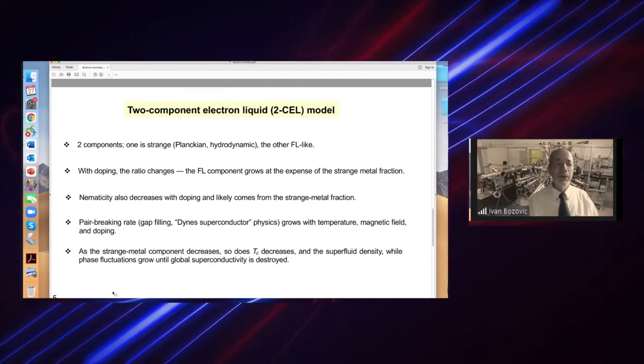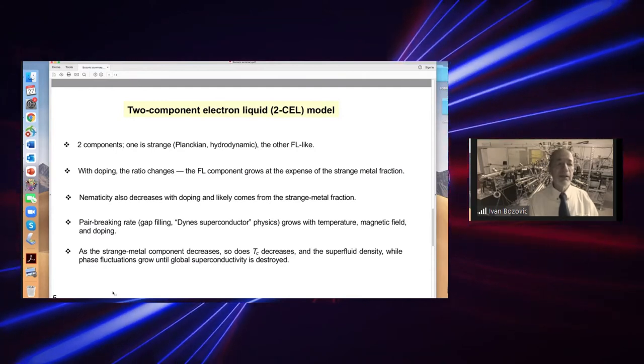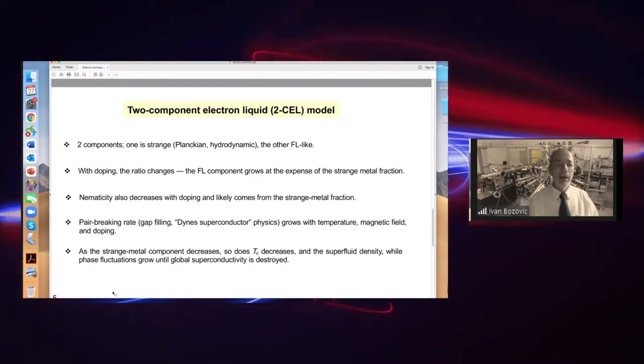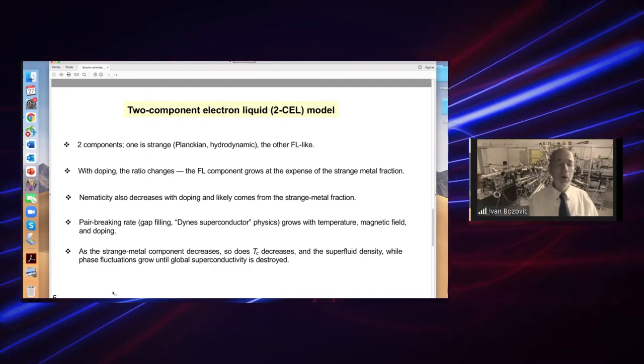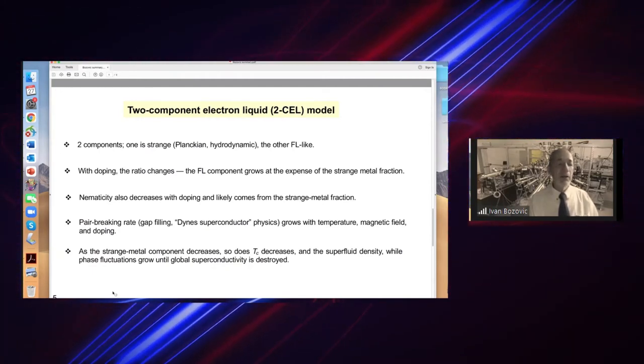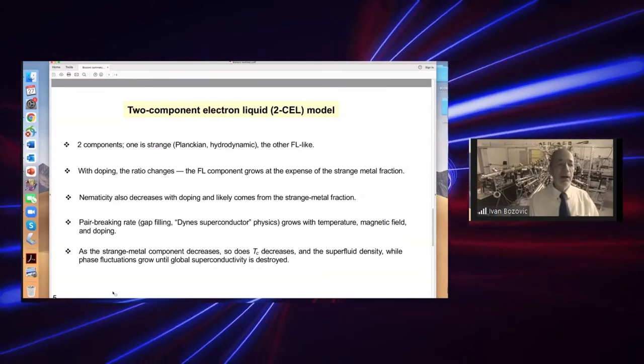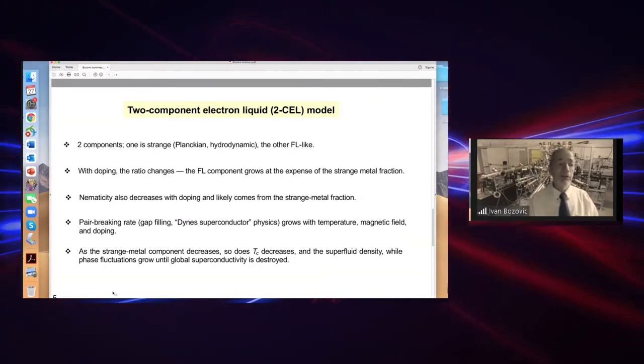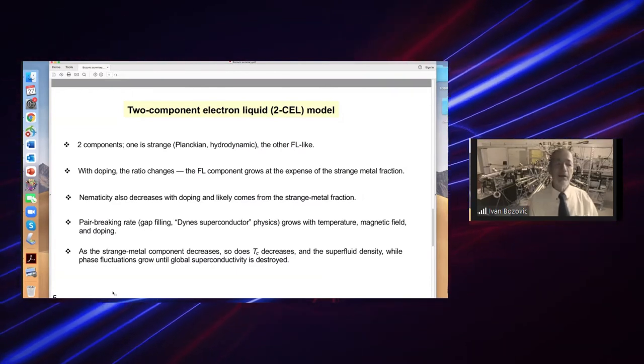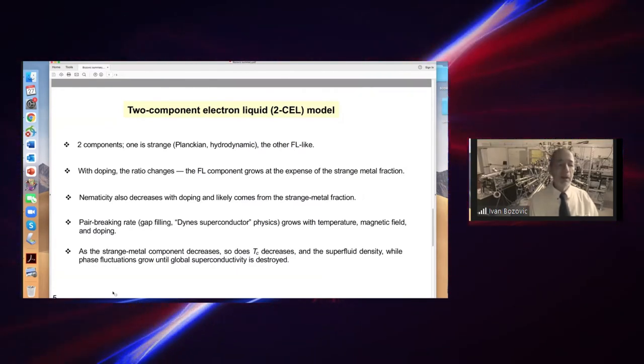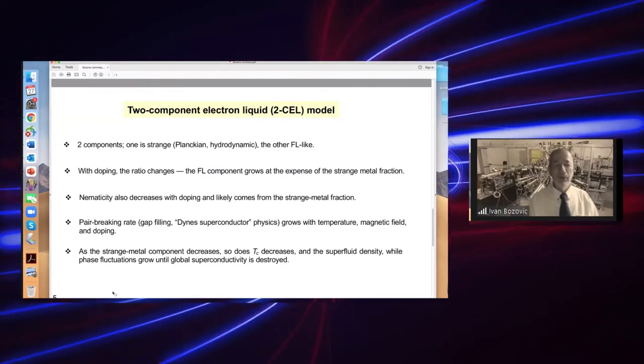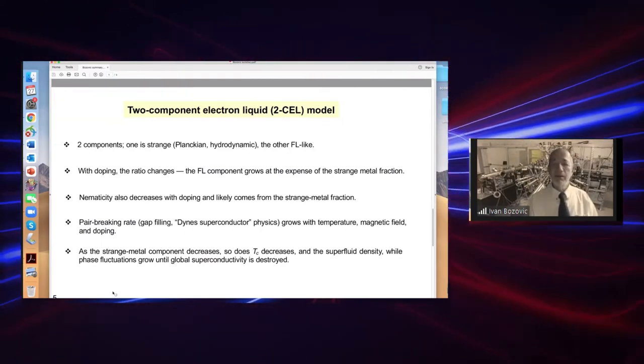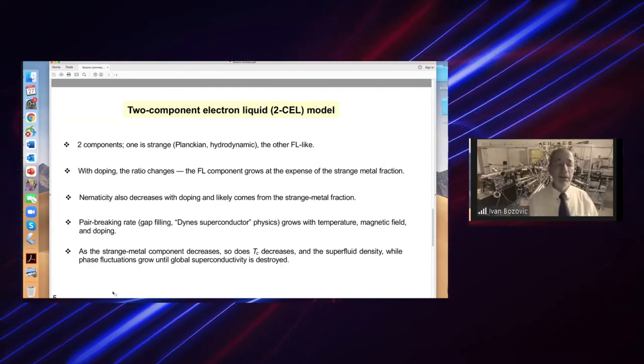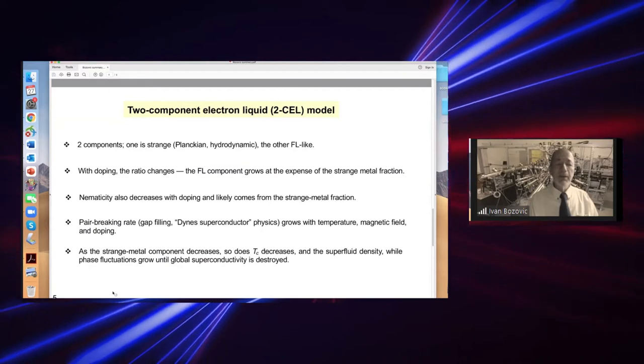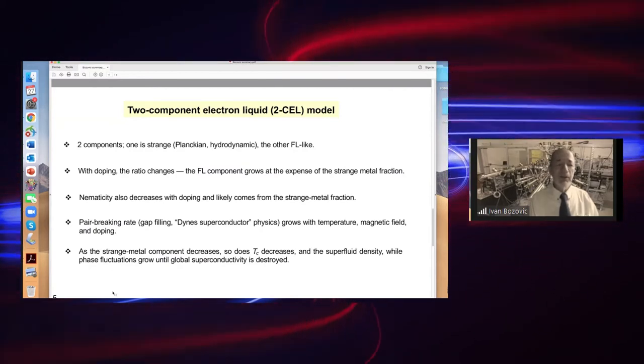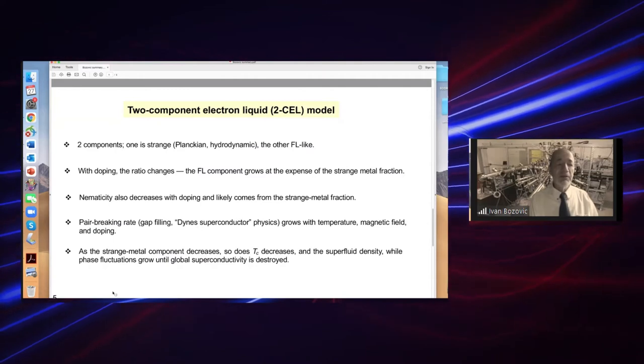The strange component, on the other hand, shows a resistivity that is linear in temperature and magnetic field, and it violates strongly the Kohler's scaling law. This strange component decreases with temperature, magnetic field, or doping, and it vanishes at the edge of the superconducting dome. So it tracks the nematicity amplitude, and very important, it also tracks the superfluid density and Tc. Therefore, it appears that high-temperature superconductivity originates just from this strange component.